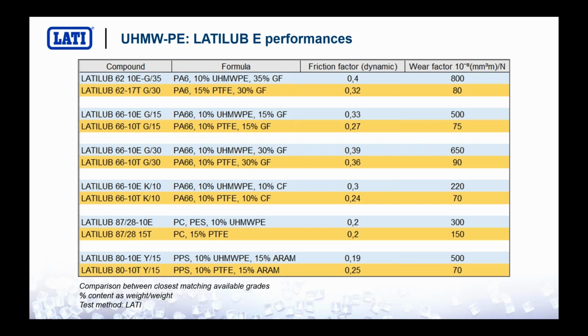What you see here is that from a friction point of view, polyethylene works fine, but as far as LATI experience is concerned, we were not able to assess a satisfactory friction wear performance. So friction is okay, wear is not okay. Why is wear not okay? We are strongly convinced that the main issue is dispersion of the filler. So it is a technological issue. It's not, I would say, a chemical issue.